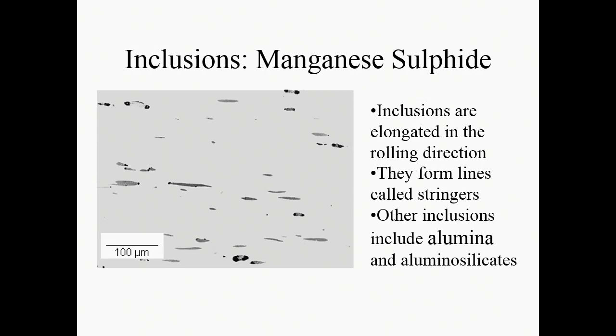So if you polish the surface, in this case it hasn't been etched, it's just been polished, what you can see in a pipeline steel that's been rolled in this direction is that you get these elongated precipitates. And they're largely manganese sulfide, but they can also be pieces of silicate, which came out of the blast furnace linings that are mixed in with the metal and can't be removed. So they're all still there. And they tend to be elongated in lines, which we call stringers.